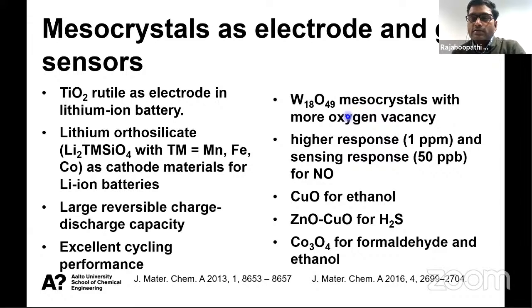And tungsten oxide they have used as mesocrystal to detect, to sense. It has a different oxygen vacancy. So when you prepare this material as a mesocrystal, the sensing has increased. For example, high response, and the sensing response is 50 parts per billion for nitric oxide.